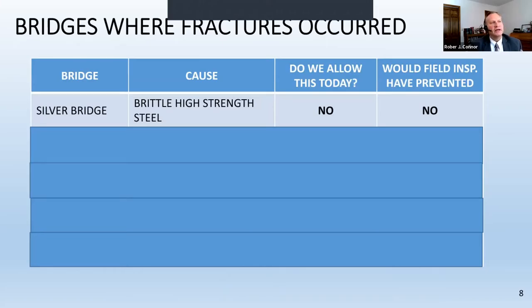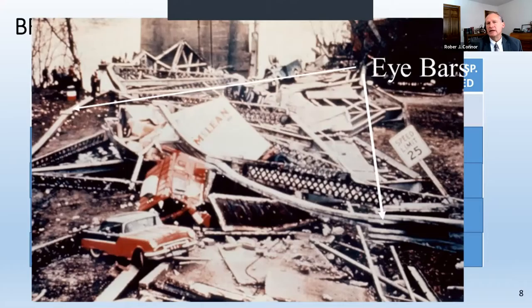It was a bridge built from high strength steel. It was built in the early 1900s, circa 1920, and it was an eyebar suspension bridge over the Ohio River. Now, the bridge was supposed to be a cable suspension bridge, but the contractor elected to use eyebars as a substitution. It was approved and the bridge was in service. However, in 1967, the bridge collapsed, a very famous failure. The failure was due to the very, very high strength steel, over 100 KSI steel or 690